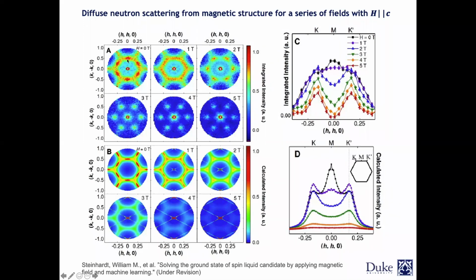At 0 field, you can see that there are excitations happening at a high symmetry point called M. But when we go to 1 Tesla, it becomes more homogeneous. When we get to 2 Tesla, the spectral weights have moved from the M point to this corner, which is a high symmetry point, the K point. And then when we go to 3, 4, and 5 Tesla, as expected, it starts to weaken. So this was one of the very important features that we discovered, and we decided to look into it more carefully.